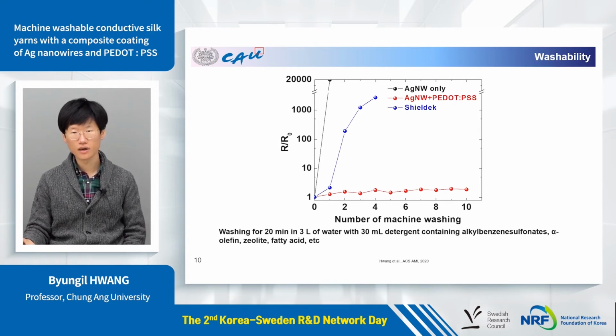So the results show the commercial yarns show rapid degradation of the electrical property after only 2 cycles of washing. However, our silver nanowire and PEDOT:PSS coated yarn show no significant increase in resistance even at 10 cycles of washing. So clearly, our yarns showed much better washability compared to the commercial ones.